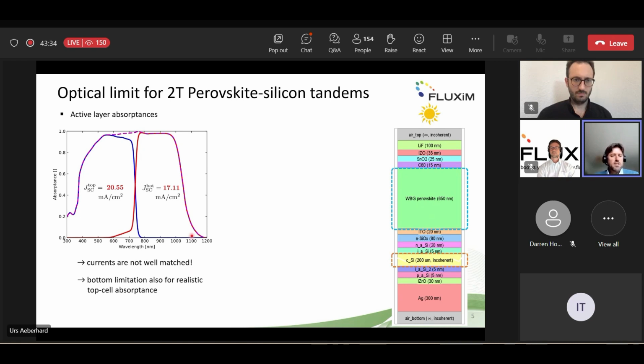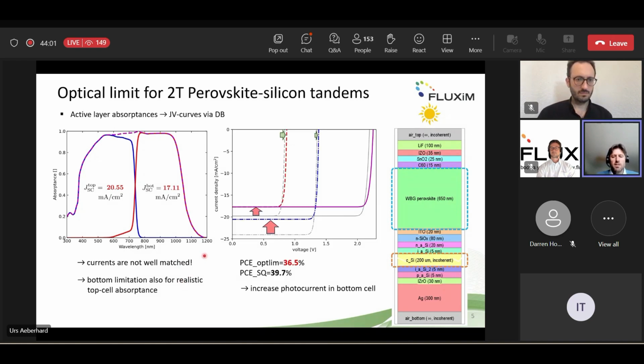What you can also see is that the short circuit current that you compute based on that is not well matched. So even in this situation where you have a finite thickness of the top cell that allows some part of the light in the higher energy domain to be absorbed in the bottom, we have a bottom limitation. Now we can use this absorptance to compute the current voltage characteristics and then the power conversion efficiency at this optical limit, as I call it.